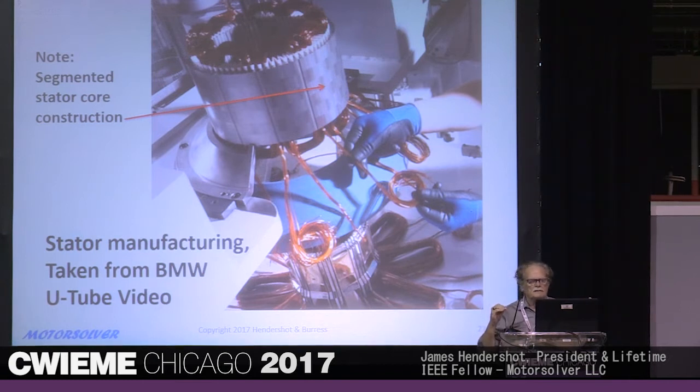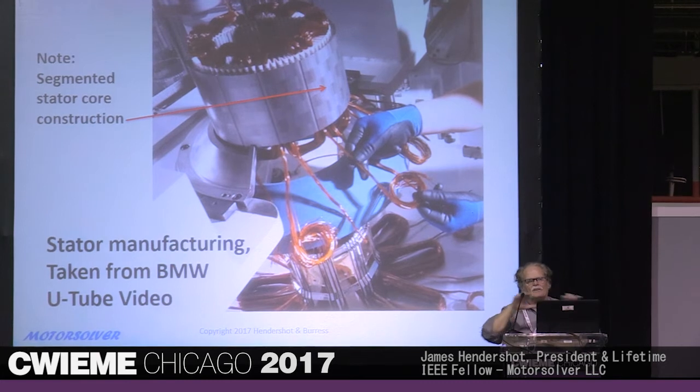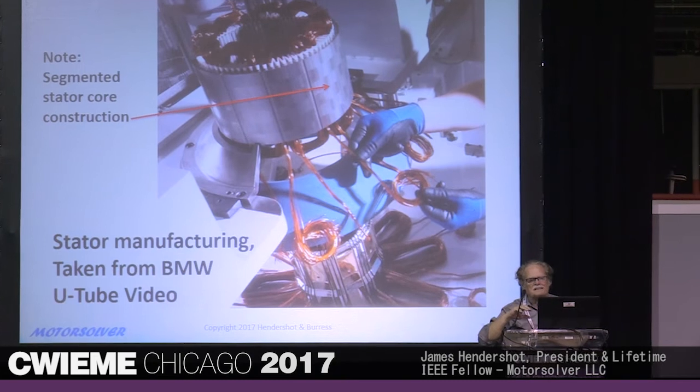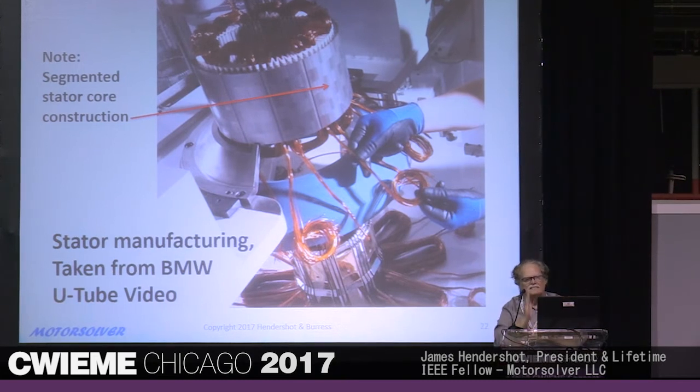And so for electric motors, since they're round, you use unoriented electrical steels, like M19, for example. But in spite of being non-oriented, there's still a slight orientation in the rolling direction. See, if you take an ingot of steel and roll it out into a strip, the rollers roll it in one direction, so there's a slight orientation in the rolling direction. Now, what does oriented mean? It means that the permeability in this direction is higher than it is in the orthogonal direction, opposite the rolling direction. And that does make a difference in the performance of some machines, like step motors, for example.